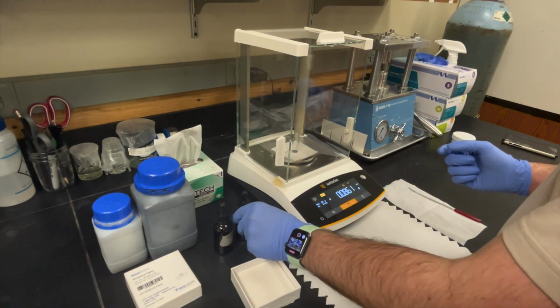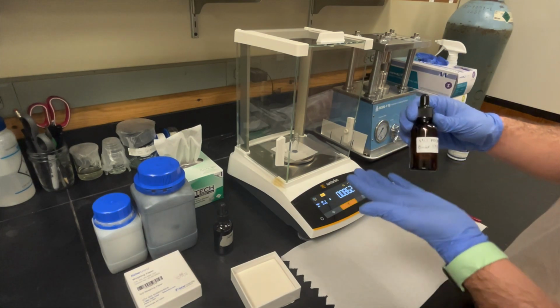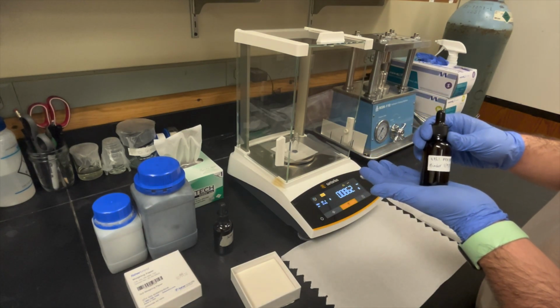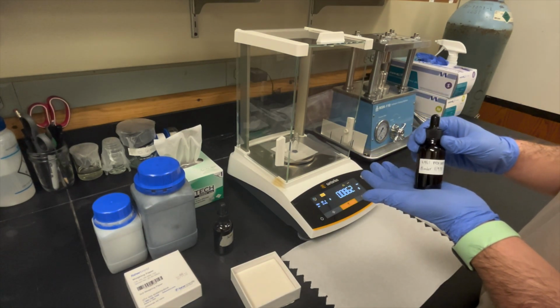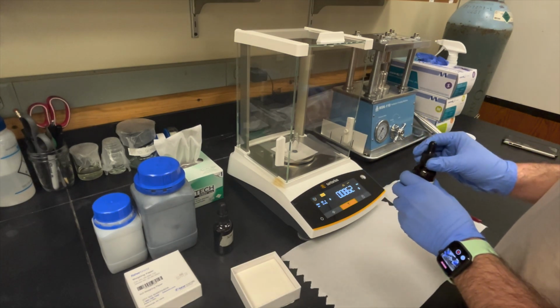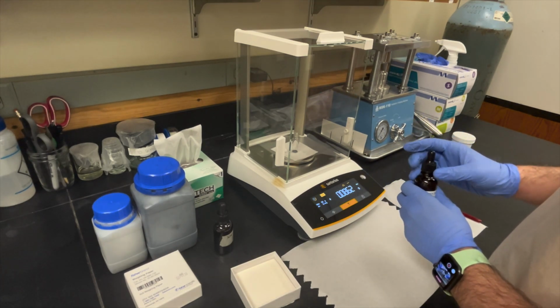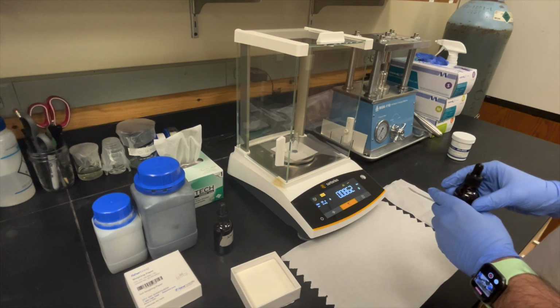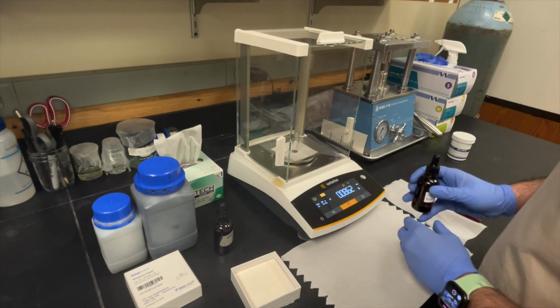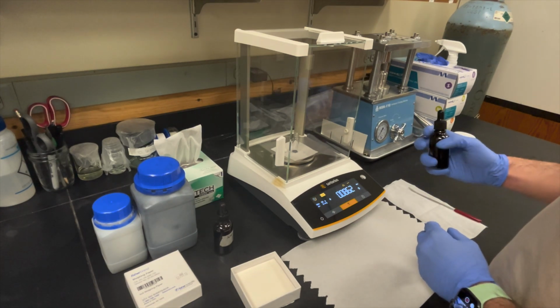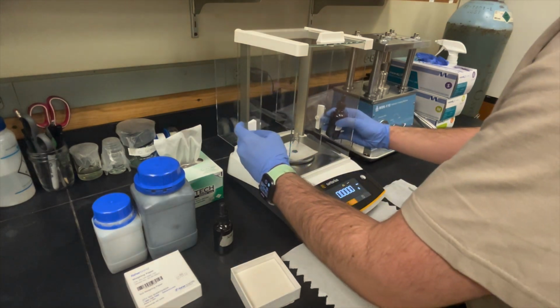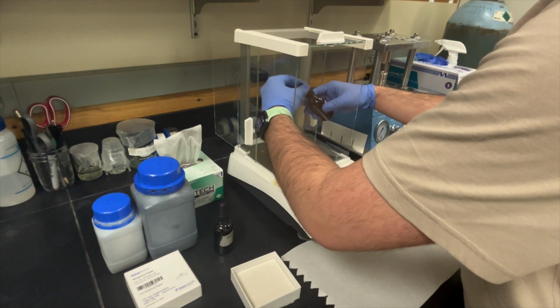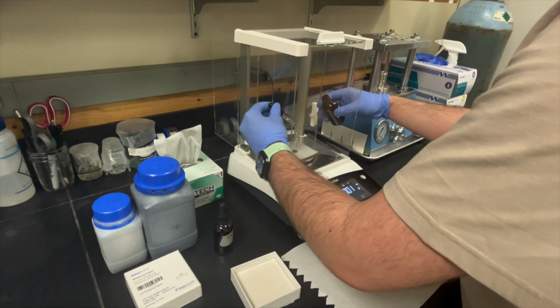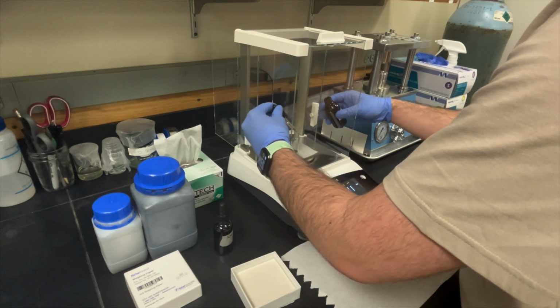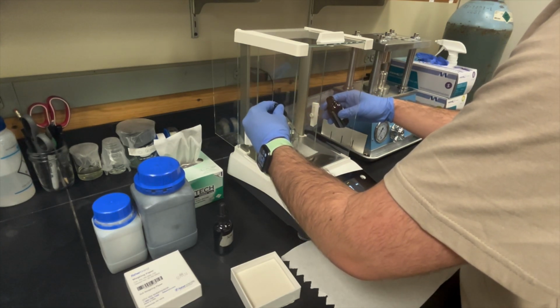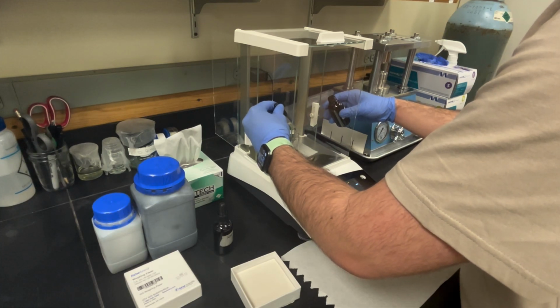We are now ready to add the binder solution, which contains 5% PVDF powder by mass. Because of this, we will need to add enough binder solution so that the 5% of it totals at the desired 10 milligrams of PVDF powder. We will need to add 200 milligrams of binder solution in order to get a total of 10 milligrams of PVDF. With this dropper bottle, this will come in between 6 to 8 drops.